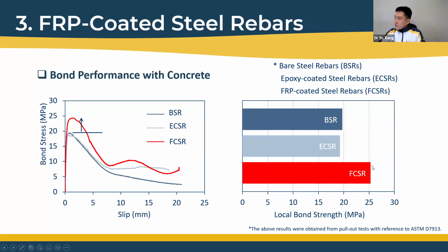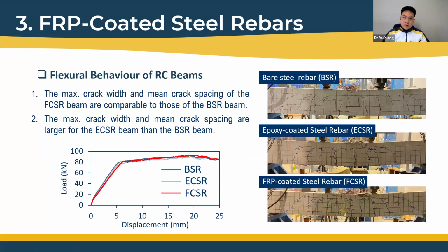Because of these results, if we design a steel reinforced concrete structure using FRP coated rebar, we do not need to consider a reduction factor for bond performance. If we use epoxy coated steel rebar, for example when estimating the anchorage length of the rebar, we need to consider a reduction factor of the bond strength, which is normally smaller than 1.0, meaning we need longer anchorage lengths. So this is the bond performance with concrete.